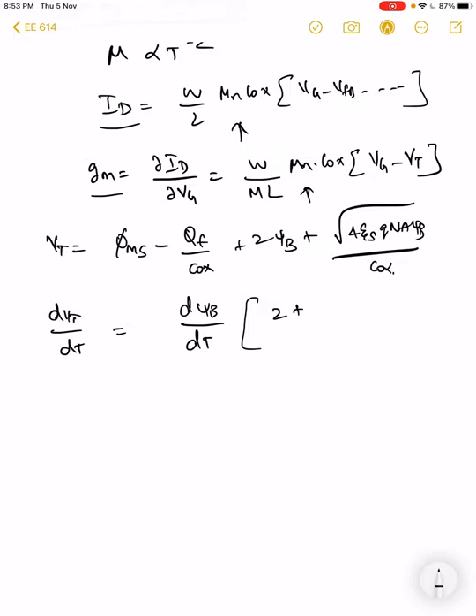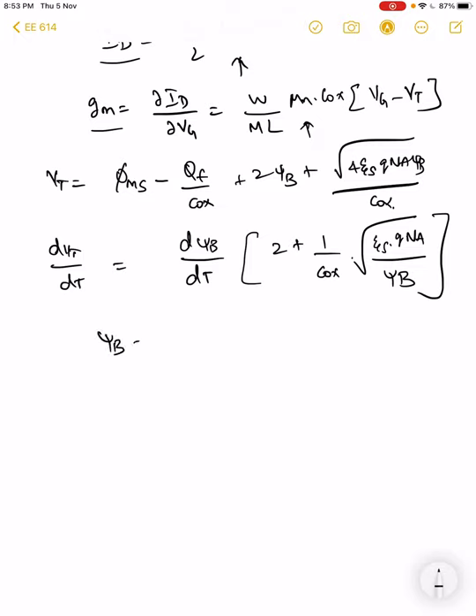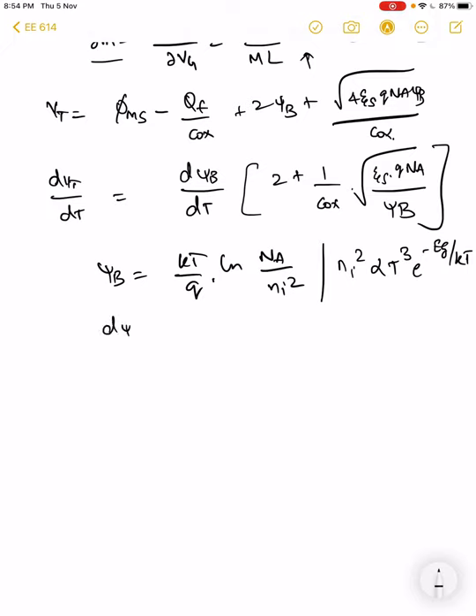Other things, the metal semiconductor, we don't think that changes a lot. Metal work function, we don't think it changes, because you see this psi ms is electron affinity minus work function, right? So that does not change as a material parameter. C ox, root of epsilon s q NA by psi b. And psi b is basically kT by q ln NA by ni, which we saw previously. And ni square basically goes as T cubed e power minus Eg naught by kT, right? And if I incorporate all these into this, d psi b by dT will turn out to be 1 by T (psi b minus Eg by 2q).